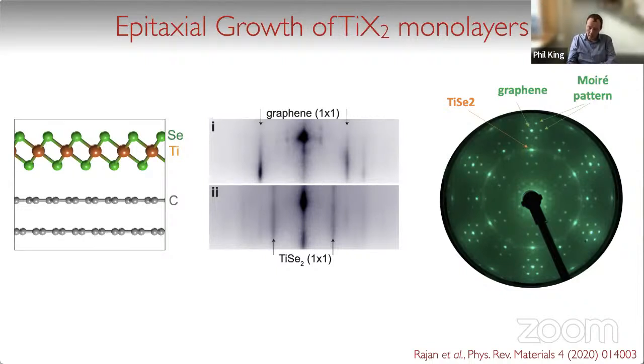So if you look in the LEED pattern here, you see that the TMD monolayer, or at least its Bragg spots, are strongly peaked in epitaxial alignment with the graphene. There's a little bit of azimuthal disorder of these still, but it's not too bad. And so it's a nice balance between enough interaction to get something that's epitaxial, so we can study the electronic structure in k-space properly, and a weak enough interaction that we don't think it's strongly perturbing the physics that's going on in the TMD layer.